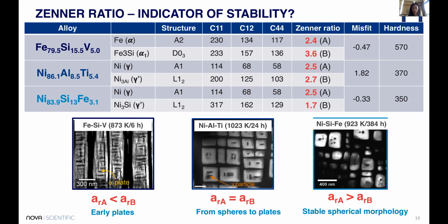Now let's switch gears and look into morphological stability of these hierarchical particles. Our iron-based alloy here shows a super fast evolution of hierarchical particles. Alpha plates are already observed after only 6 hours of aging. Other alloys, such as the nickel aluminum titanium alloy, initially show gamma spheres, and plates only appear after 24 hours of aging. The nickel silicon iron alloy mentioned earlier shows gamma spheres remaining spherical up to 384 hours of aging.